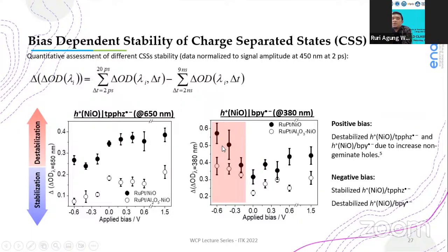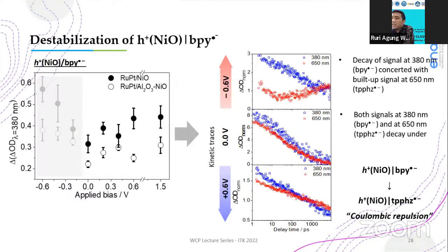So to get the answer, we check the kinetic traces at 380 nanometers and 650 nanometers associated with the BP and the TPPHZ ligands, respectively, under different applied bias. As shown here, under negative bias, both BP and TPPHZ signals decay, but after 100 picoseconds, we can see the TPPHZ signal builds up. However, under zero and positive bias, both signals only decay up to the longest experimental window. And this, we suggest, is because the BP anion is pushed toward the TPPHZ ligands, which is possibly due to the Coulombic repulsion by the external electric field.